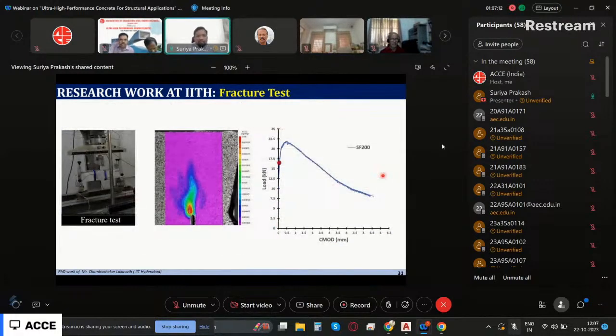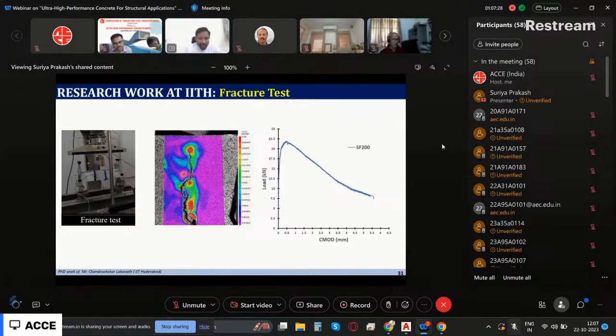Then another thing is evaluation of your material properties. So this is the UHPC that was tested in fracture. That means I put a small notch and then I keep pushing it, and I see how the crack is progressing. If the crack formation is delayed and if fibers are able to arrest the crack well, then it is a very good design. So this is what we call a fracture test.